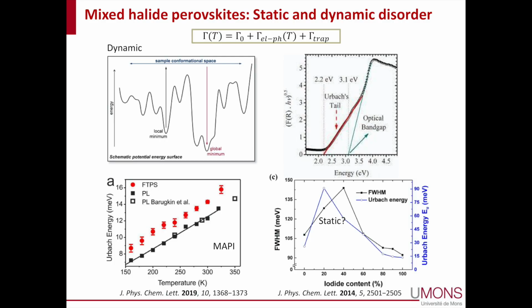Although when you have mixed halides, this is shown here. This is not the full width at half maximum, but it's related to the Urbach energy. You can see that in the mixed case, the full width at half maximum is significantly larger than the values for the pure phases. And so this is something we would like to understand.